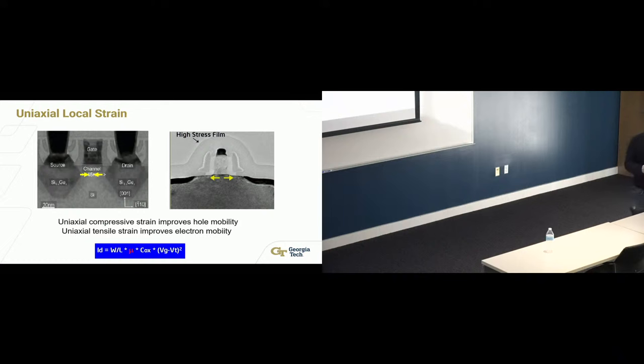The question was that the traditional approach was to create a virtual substrate, epitaxially grow something that is compressively strained. People have done that, and then you actually improve the PMOS mobility. But if you do that, the same compressive strain will appear on the NMOS side because it's a universal strain. And then the electron mobility will go down. So you'll improve PMOS performance, but you will actually decrease NMOS performance. So we had to come up with an alternate strategy, where the electrons like exactly the opposite thing.